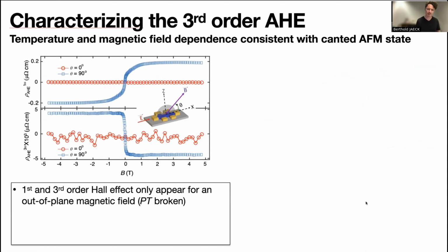In order to understand this observation, we moved on to characterize the third order anomalous Hall effect. The first thing we did is to check on the symmetry constraint. We know if the spin is not canted out of plane, there should not be a third order anomalous Hall effect. So what we've been doing now is a rotatable sample holder that allows us to rotate the sample from the out of plane to the in plane direction. Shown in blue here is now the result when the field is applied along the out of plane direction of our Hall bar. And this basically reproduces what you've seen on the previous slide.